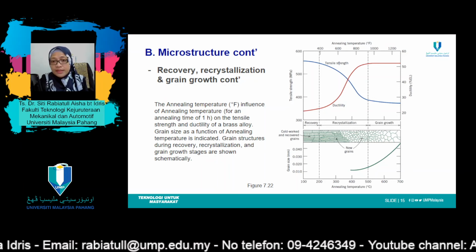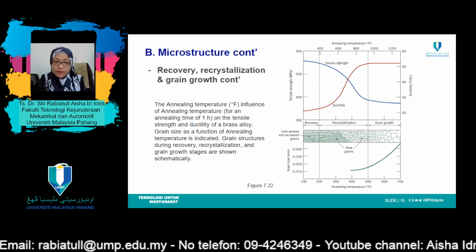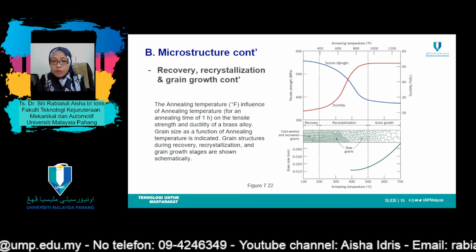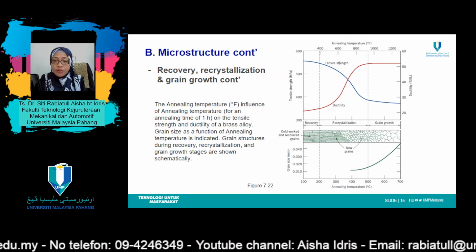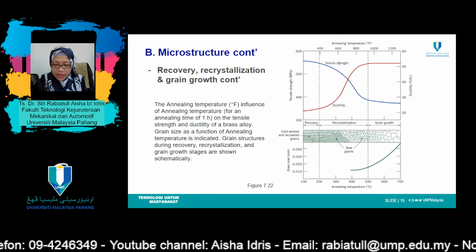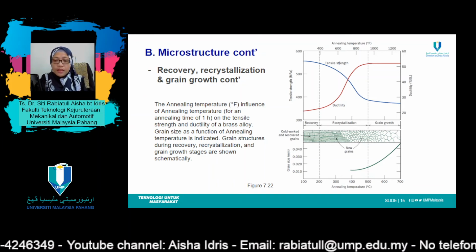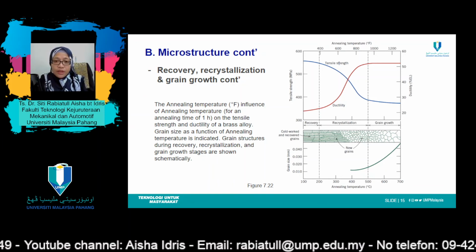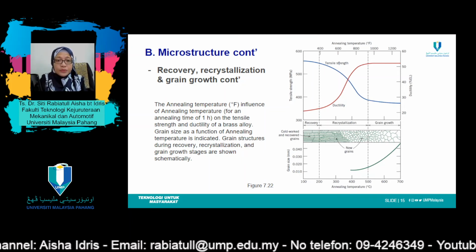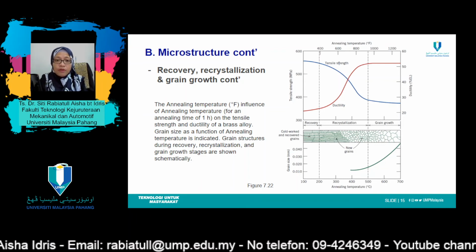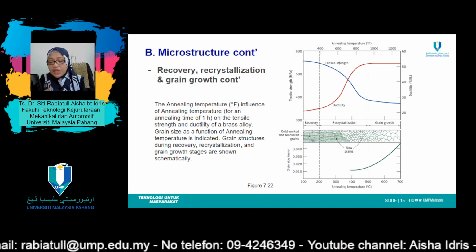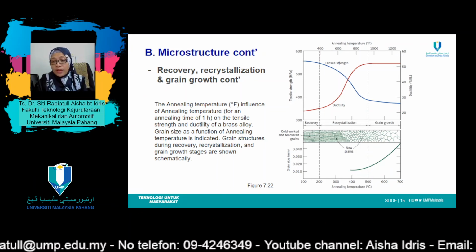During recrystallization, grain boundary motion occurs as the new grain nuclei form and then grow. It is believed that impurity atoms preferentially segregate and interact with these recrystallized grain boundaries so as to diminish their mobilities. This results in a decrease of the recrystallization rate and raises the recrystallization temperature, sometimes quite substantially.